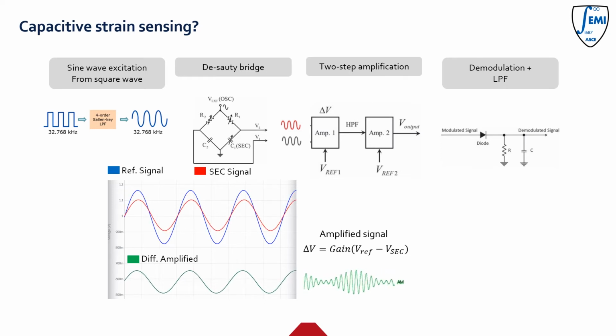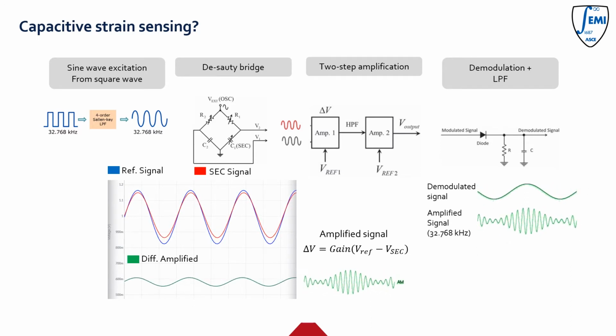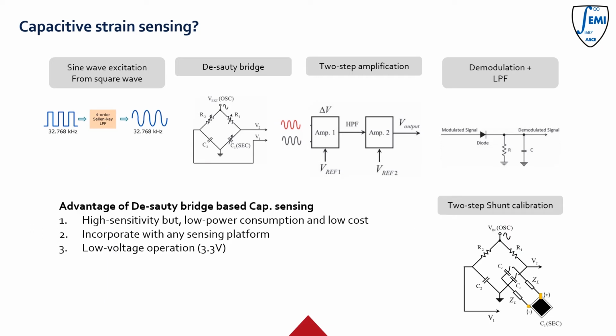Only the SEC side signal amplitude changes according to the SEC strain variation, shown in the red signal. The two signals are fed to a differential amplifier to catch the SEC signal's amplitude variation, and the difference, shown in the green signal, is amplified for maximum sensitivity. After that, the amplified signal was enveloped using a demodulation circuit and low-pass filtered for output.